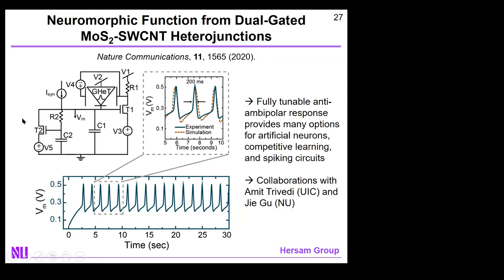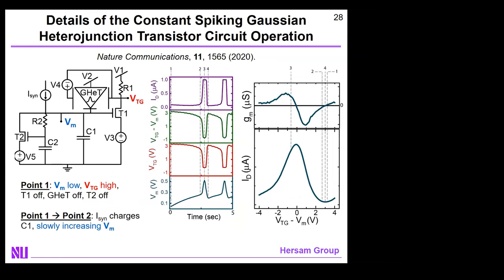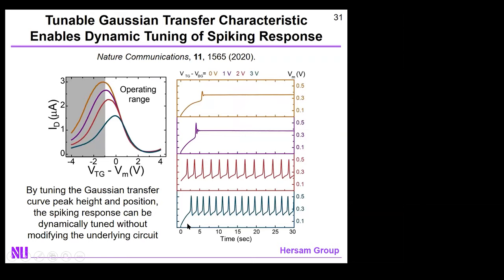And here the active elements are down to 3. Perhaps we can do better, but even if we can't, this is still a significant improvement over what you achieve with silicon CMOS. But to me, what's more interesting is that in silicon CMOS, you can design a particular circuit for a particular response, and then if you want a different response, you have to design a new circuit. Whereas here, as I noted briefly in this slide, we don't need to redesign the circuit, we just change the biasing to the dual-gated Gaussian heterojunction transistor, shifting around its antiambipolar response, and that dynamically changes the spiking. So this is a much more reconfigurable device and circuit than you would have in conventional silicon CMOS.